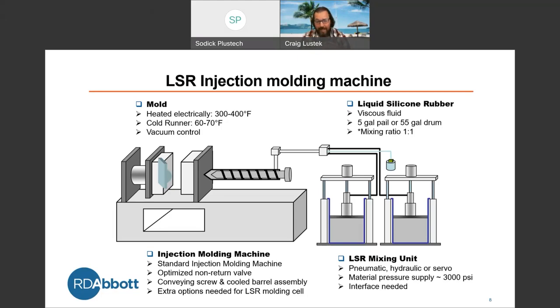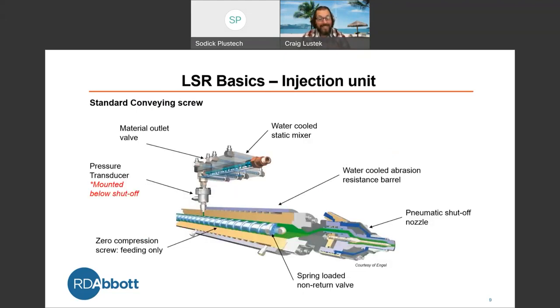The injection molding machine, again, is a standard injection molding machine, but we're changing a few things. For example, an optimized non-return valve, a conveying screw, and cold barrel assembly, extra options needed for that LSR molding cell. When we look at the LSR mixing unit, we can go pneumatic, servo, or hydraulic. Material pressure supply is roughly 3,000 PSI. And again, that can change depending on your part size, shot size, type of material you're running, and the interface. We always talk about a closed loop system for that LSR interface. We need that to ensure we're getting consistent fill.